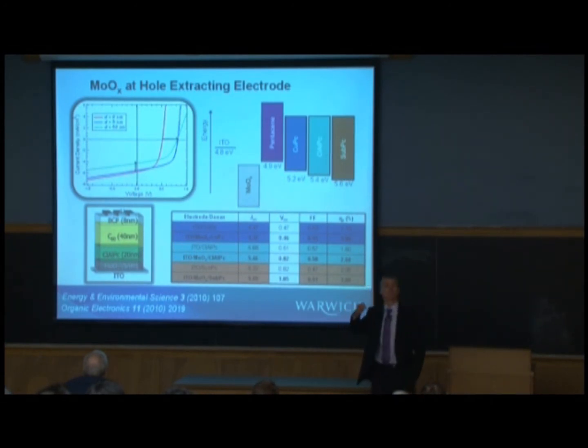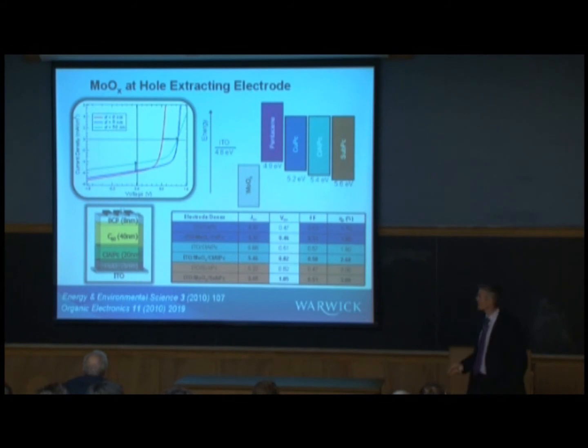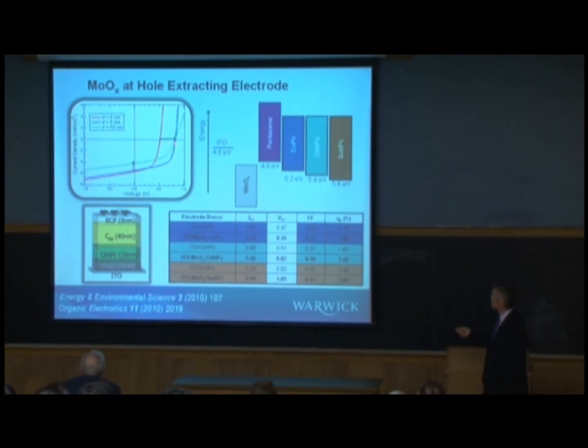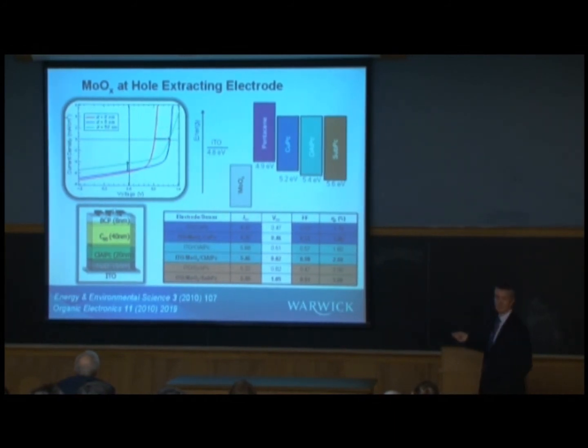If you go too thick, in this case 50 nanometers, then the voltage is fine, but the current now drops very significantly because the very thick layer prohibits good charge mobility to the electrode. So there's a compromise of the thickness of the molybdenum oxide you can use, and 5 nanometers actually is the optimum for these particular devices.